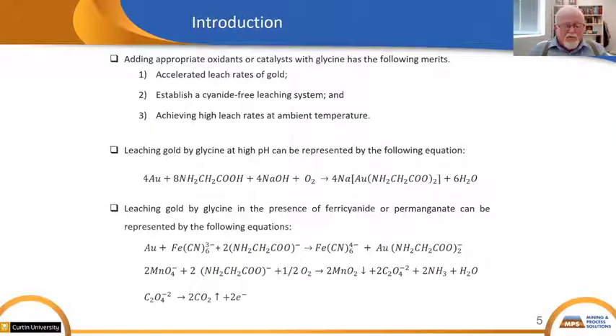Okay, here is some of the chemistry of our cyanide-free systems. I do not propose to go over the equations during the talk, but present them here for your future reference. So at any rate, there are reasons for adding various additives to glycine, and they are: one, we get accelerated leach rates of gold. Secondly, we can establish a cyanide-free leaching system. And three, we get high leach rates at ambient temperatures.